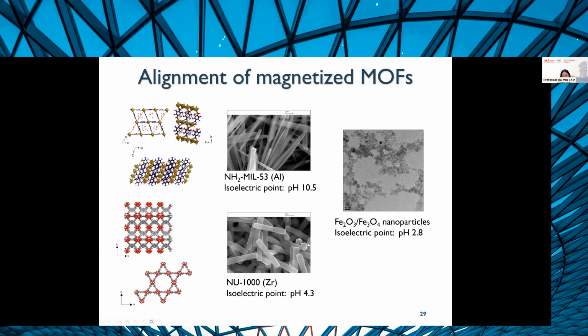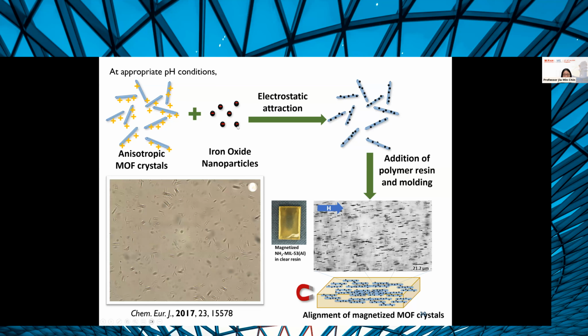So below these isoelectric points, if they are at a pH of, let's say, 3, these MOFs happen to be positively charged. Then we took some iron oxide nanoparticles, and these nanoparticles have an isoelectric point which is quite low, of 2.8. Above this isoelectric point, these particles are negatively charged. So you see where I'm going with this. If you have positively charged MOF crystals and negatively charged iron oxide, these are already preformed, you just mix them together and they stick to one another. So these iron oxide nanoparticles that we synthesize, we mix them and they just stick onto the external surfaces of our already preformed MOF crystals. And this is a very universal approach. Just by playing with which pH condition you use and the functionalities on your iron oxide or other types of magnetic nanoparticles, you can really just create a magnetic envelope around your MOF crystals.